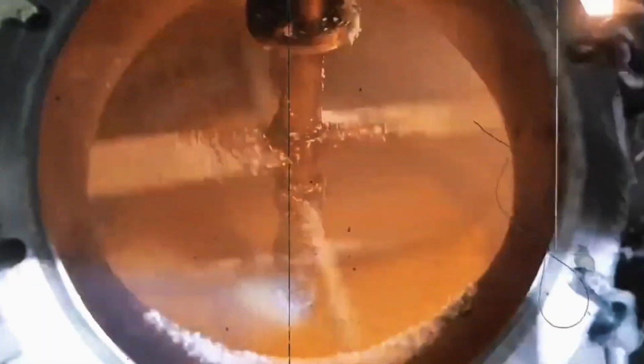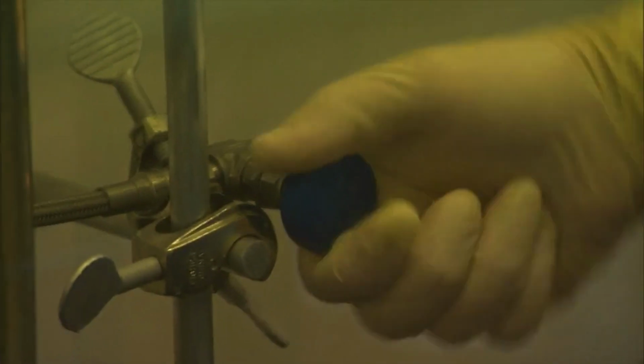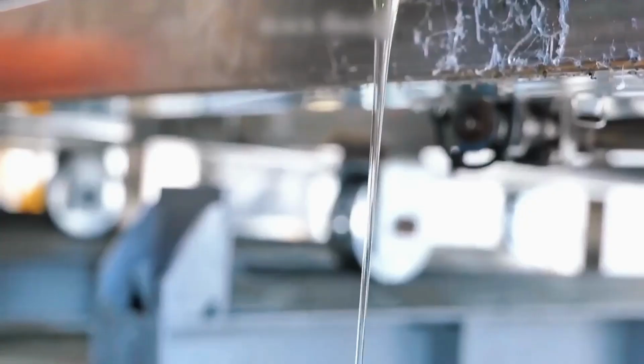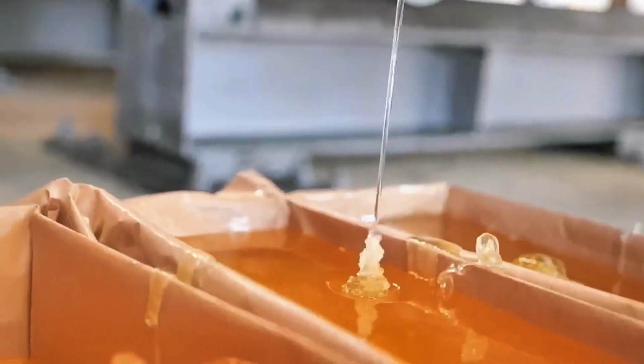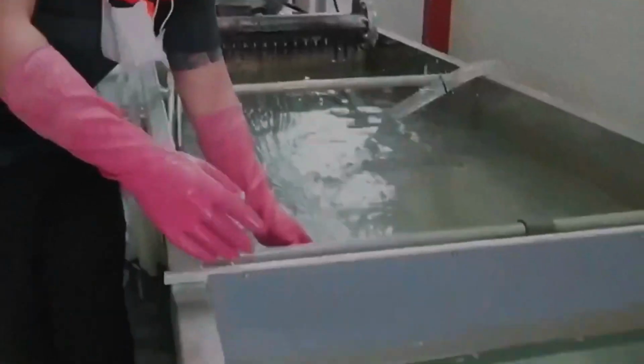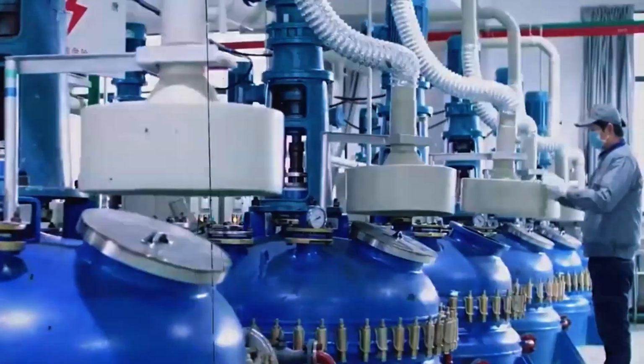To optimize the process, catalysts, usually organic acids, are used to make chain breaking easier without needing to raise the temperature too high, reducing energy consumption. The residues that fail to evaporate are not discarded. Instead, they are collected and recycled for another cracking cycle, an important detail in an industry that strives to minimize waste whenever possible. Throughout the procedure, a constant flow of nitrogen is maintained. This inert gas pushes out moisture and oxygen that could trigger unwanted reactions. At the same time, pressure sensors ensure there are no leaks, since any air intrusion would compromise system stability. Thus, a thick syrup is transformed into a crystal clear liquid, ready to become the heart of the adhesive.